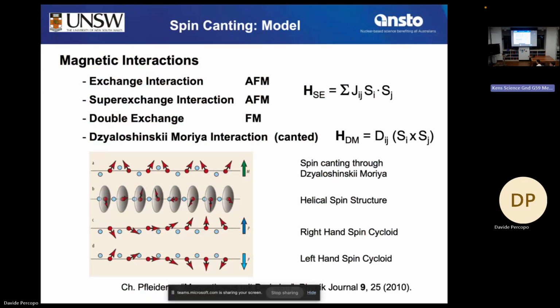Yeah, sorry for erasing that. So if you have a crystal lattice which contains triangles or honeycomb structure, that's actually realized quite often. Kagome lattice, spinel structure, graphene, honeycomb-like. So we place the first spin here and the second spin here, which would be antiferromagnetic. And now, what should this third spin do? Because that's ferromagnetic, parallel, and that's antiferromagnetic. So simply spoken, that third spin doesn't know what to do. That's called geometrical frustration. And that's one of the three options where quantum magnetism starts.